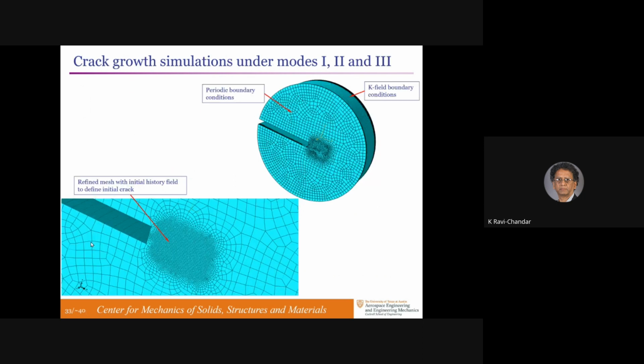All right, so it's a very unsatisfactory description of the phase field method, but we said let's implement this and see what it does for the problem of mode 1+3 fracture. So we created a very fine discretization of the crack tip regions to be able to see how a mode 1+3 loaded crack will grow. So we simulated only a small domain near the crack tip, applied K-field boundary conditions, meaning displacements based on the K1, K3 field were applied at this location. And that's at about 10,000 length scales L naught away from the crack tip, to give you an idea of how long we had to go.